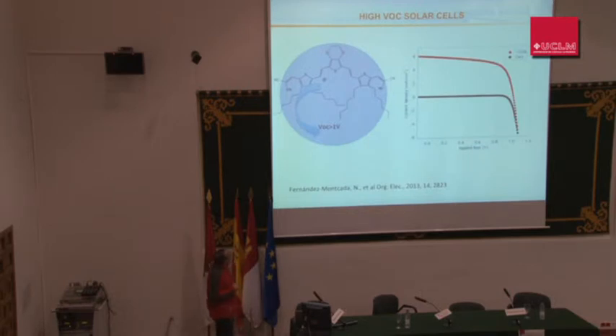So we have studied in much detail these molecules with the A unit and the two cyano groups, and you can see here the same approach: a pi bridge with these two strong acceptors. The important thing in these molecules is that you cannot find many examples in the bibliography with such a huge voltage. This is over 1 volt, among the highest voltages for a solar cell. Silicon modules you can buy have a voltage around half of this, 500 millivolts. The best silicon you can have is 750.